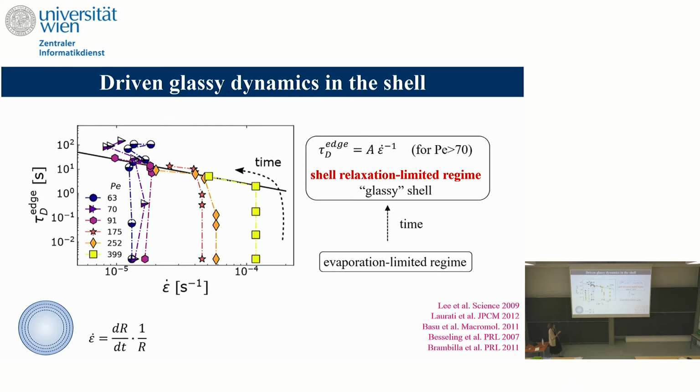In this regime, you have a relaxation time which is inversely proportional to the rate at which you force your system, and it has been observed in a lot of solid-like materials: colloids in 2D, in 3D, polymers, and so forth. It's really a solid-like regime. Remember, the shell is a glass, and what drives the relaxation is the relaxation of the shell. And this is this regime.